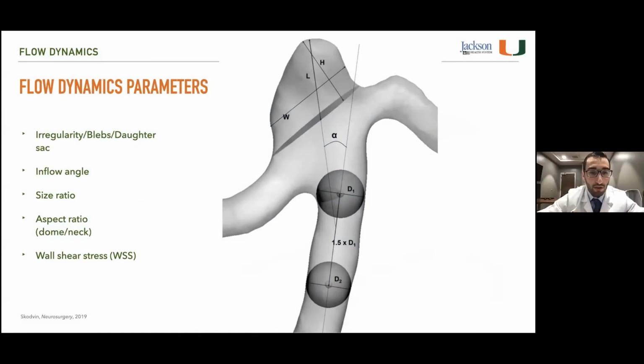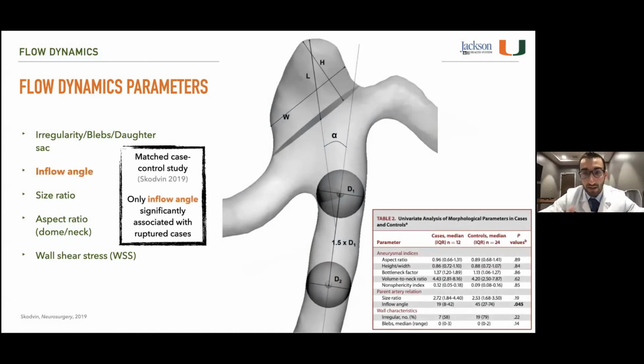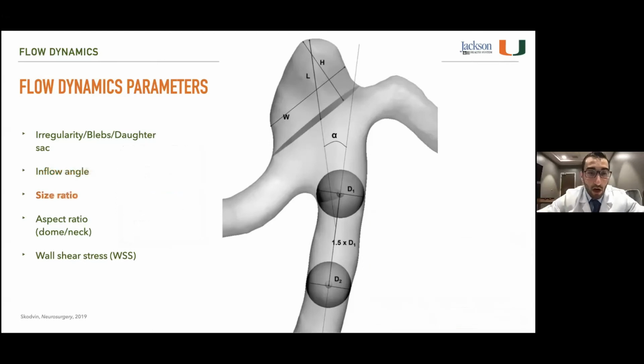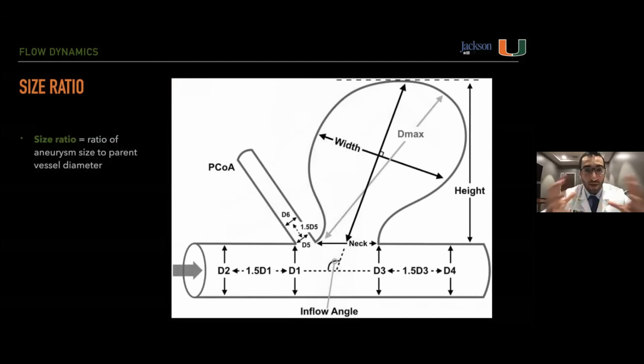So some other parameters that are looked at: inflow angle, so basically the direction in which the blood flows into the aneurysm. There's a good matched control study that shows that it's significantly associated with ruptured cases among a bunch of different parameters. Other groups have looked at size ratio. Size ratio is basically the ratio of the size of the aneurysm sac to the parent vessel diameter. And initially when I was looking at this, I found it very odd to think about why that would matter for an aneurysm.